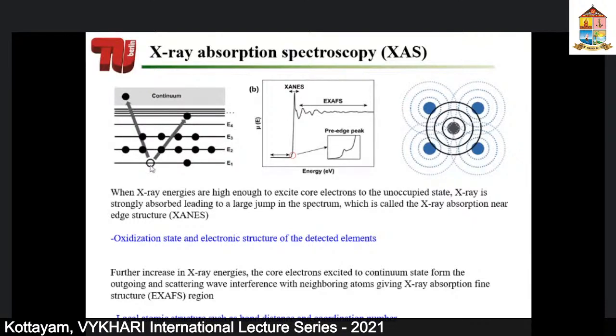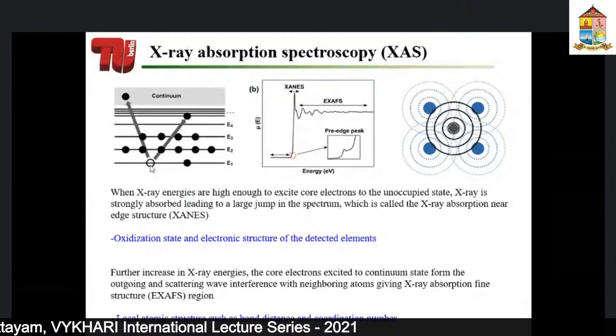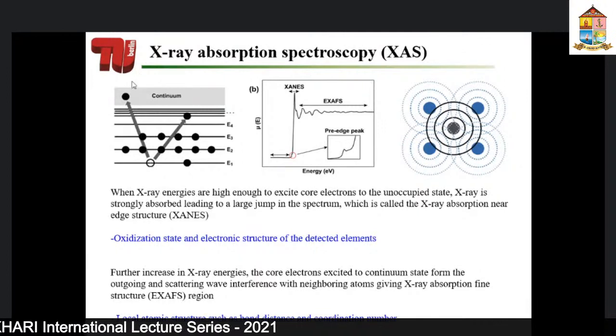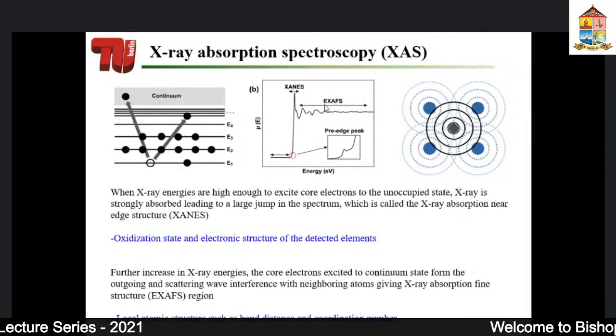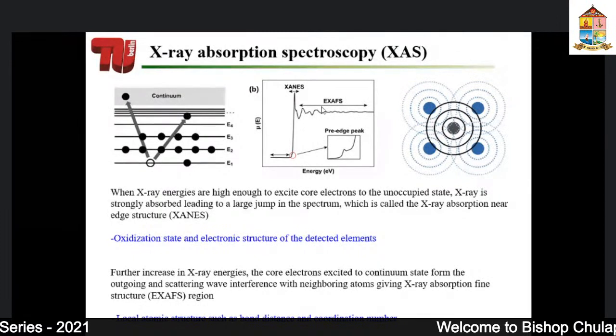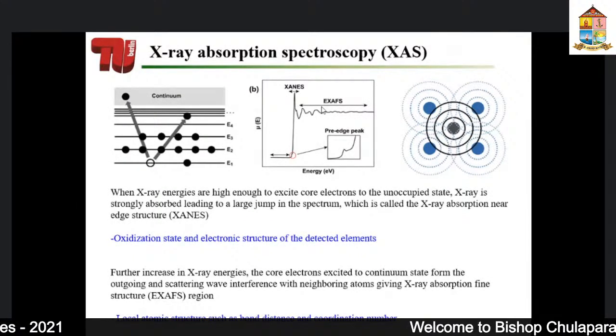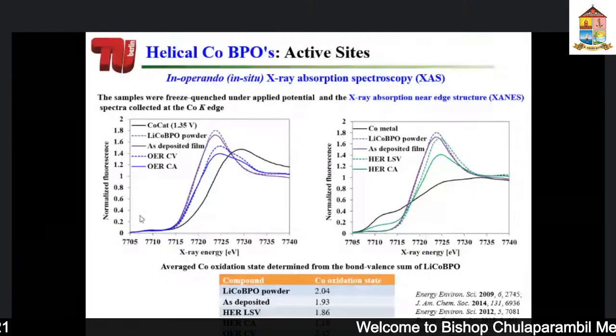But when you provide extra energy and you kick the electron out from your core level to the continuum, then this electron would interact with all the other atoms and provide you a pattern which is called X-ray absorption fine structure, which is this region, and which would give you the local coordination number and atomic structure. This is very basic, but what you get is a curve like this.